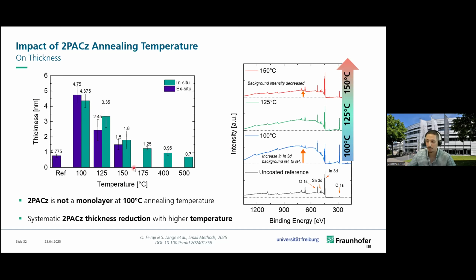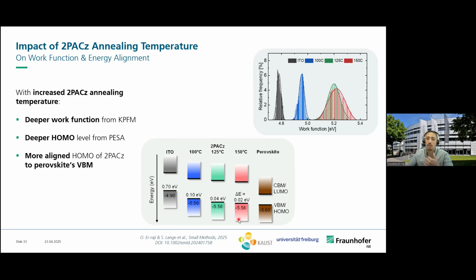And also when we did photoelectron spectroscopy measurements in air to assess the HOMO level and compare it to that of the valence band maximum of the perovskite, to get an idea about the alignment and how it changes with the annealing temperature, we saw that the delta in energy between this level and this level was really reduced when we went to higher annealing temperatures. So not only the thickness changes, but because the thickness changes, we then have changes in the orientation of the molecules, and therefore this influences the work function and the alignment.